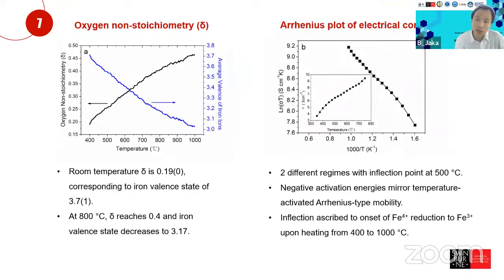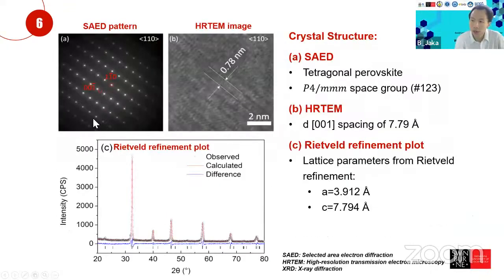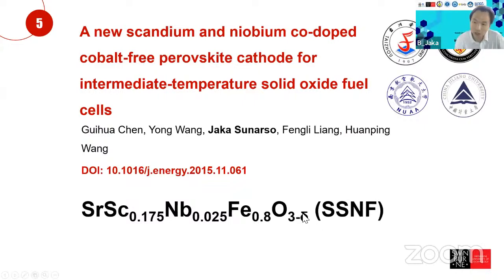And then the next thing that we want to check is the oxygen non-stoichiometry, because as you know, in the structure you have oxygen vacancies. Oxygen is supposed to have a charge of 2-. If everything here has an exact cation charge of 6+, then we will not have oxygen vacancies. But here we have a 3-δ oxygen non-stoichiometry. And the oxygen non-stoichiometry is the one that helps the transport within your perovskite lattice.